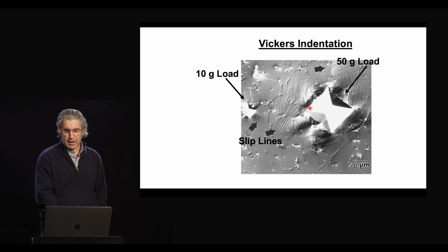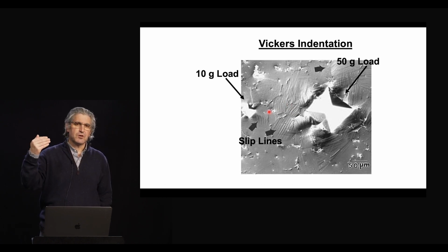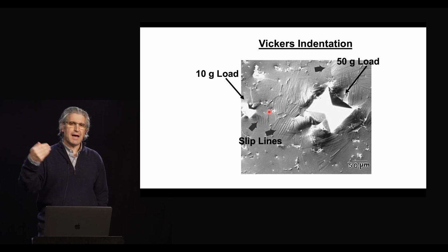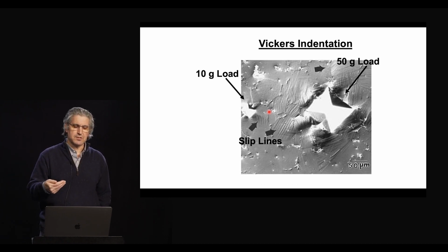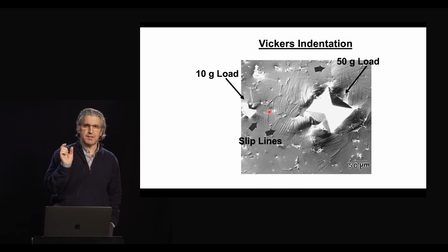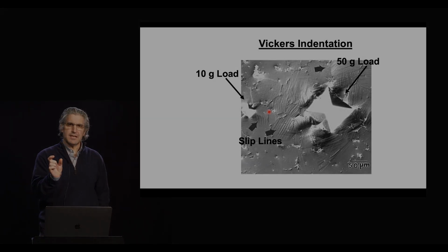It also tells us why we need to have a certain distance between materials, because this material has been plastically deformed. This is in that strain hardening range. So if we get these indents too close to each other, the first indent will impact the hardness measurements on the next one. So there's certain guidelines within the ASTM specification.